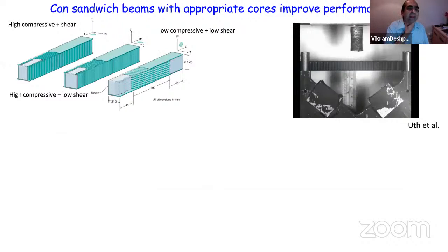So again, we are going to do baby experiments, and the aim here is not to say what the core of the sandwich is, but to ask what properties I need for the core. So we're going to take these types of sandwich beams. They all have simple hexagonal honeycomb cores, but because hexagonal honeycomb is anisotropic in its plastic properties, we can play lots of games. I can change the thickness of this core. I can rotate the core in this LW plane. And when I rotate it, I keep the compressive strength in the T direction the same, but I change the shear strength in the longitudinal direction of the beam.